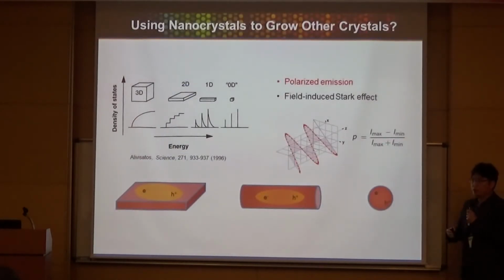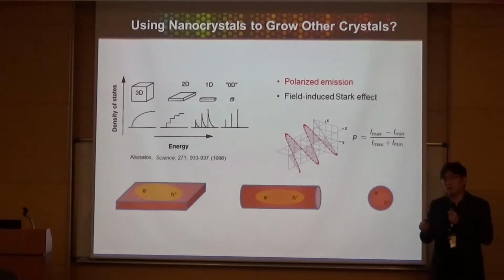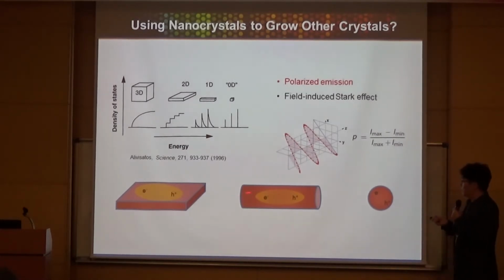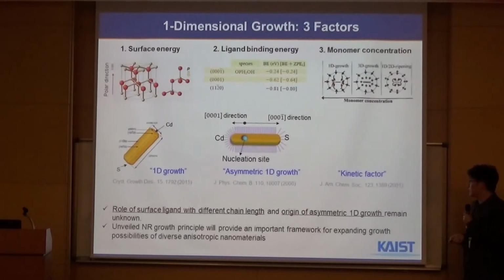And we are also exploring, in our lab, low-dimensional nanocrystals, such as nanorods and nanoplates. And our primary interest is on polarized emission that comes from these anisotropic growth. Compared to spherical or semi-spherical quantum dots, when you have nanorods or nanoplates, when they emit, because of the dipole moment aligning to the long axis of this anisotropic species, you tend to have polarized emission, whether it's linearly polarized emission or circularly polarized emission.